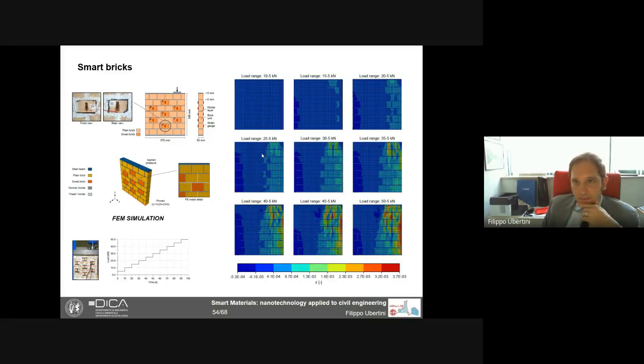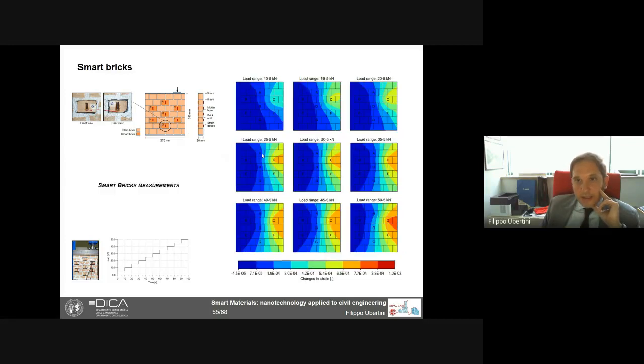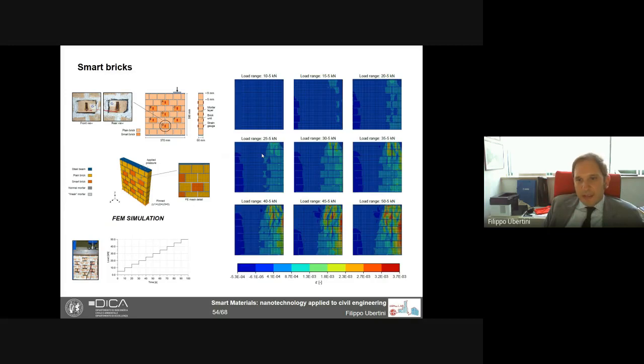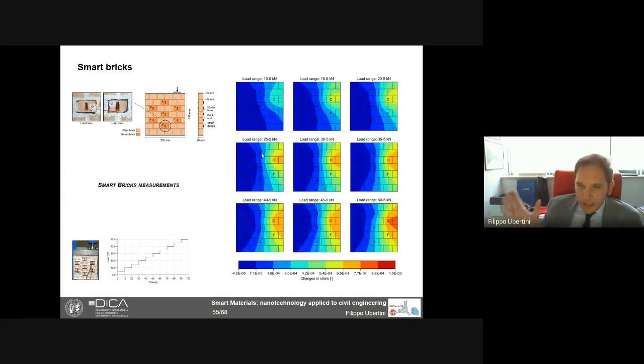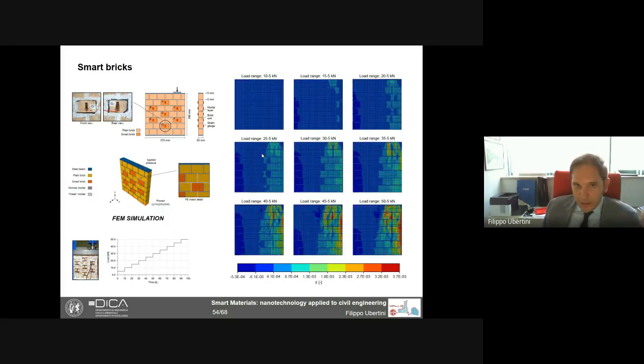If you look at the strain field from the numerical model, you will see these are the strains at the different load intensities. Then we interpolate the strains from the smart bricks. And what we find with the kriging interpolator is a map like this, that makes pretty much sense with respect to the finite element map. Of course, with the smart bricks, we have an averaging of the strain between mortar and bricks, because we are measuring the strain of the bricks and then averaging it. With the FEM simulation, of course, you have strain that is different in the bricks and the mortar. But still, we can say that there is high consistency between this map and this map.